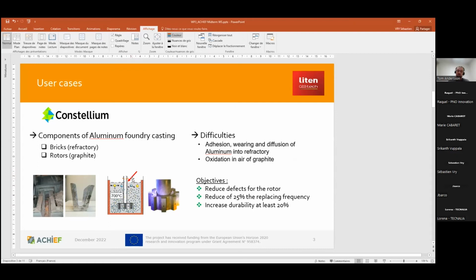The difficulties are the adhesion and wearing caused by aluminum on refractories. The melted aluminum temperature is slightly lower than 700 degrees, and in the case of the graphite rotors, they are impacted by the oxidation in air at the surface of the bath. The objectives here are to reduce defects of the rotors caused by oxidation and to reduce the replacing frequency. Consequently, it would lead to an increase of durability.